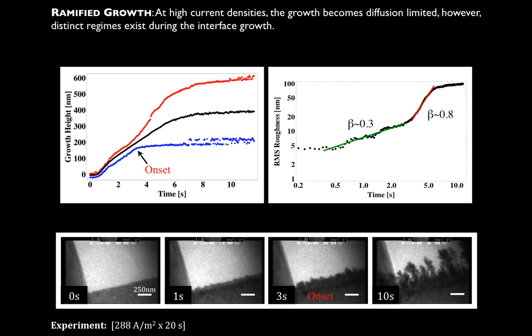When we look at the RMS roughness we see that in the very early stages, before the onset of the diffusion-limited regime, we again have that 0.3 growth exponent — just roughening with fighting between wavelengths. Then we transition to the diffusion-limited regime where the growth exponent more than doubles to 0.8. To give you the physics: in a completely random deposition where you drop particles down columns randomly, you have a Poisson process giving a growth exponent of 0.5 that goes on forever. So a growth exponent greater than 0.5 means you're depositing selectively at peaks; less than 0.5 means physics like surface diffusion are smoothing the surface. A growth exponent of 0.3 is good because it means roughening is not growing in an unabated fashion.